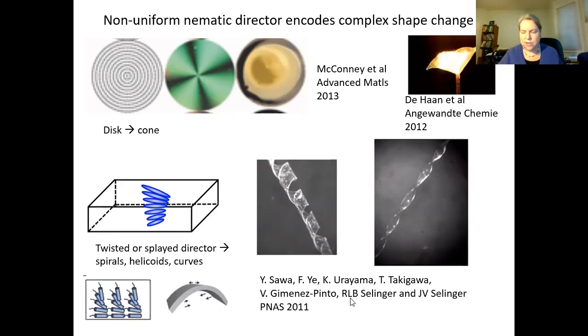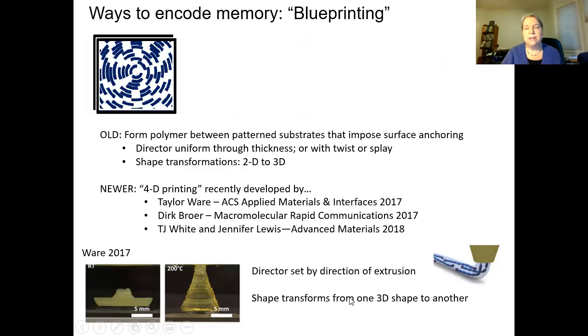So let's see, why am I not going to the next page? There we go. So the first way that these materials were patterned was to take two pieces of glass. This is, again, exactly something like you would do with the liquid crystal display, and put a surface patterning on them that causes any liquid crystal in contact with the glass to align with a certain orientation. And Tim White, who was at that time at the Air Force Lab in Dayton, had the idea that he could use a photopolymerizable coating where he could essentially shine a very thin collimated beam with linearly polarized light, and thereby set an anchoring direction, whichever way the polarized light, and that would be the anchoring direction for the material.